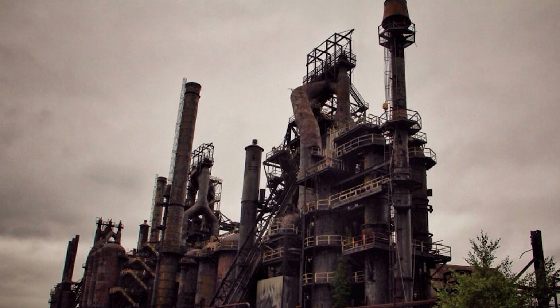Water quenching was fastest. The plate cooled from 1,625 degrees to 400 degrees in under 2 minutes. Fast cooling trapped the carbon in solution, creating a crystal structure called martensite, extremely hard but also extremely brittle. The plate emerged from the water quench hard enough to shatter glass, but brittle enough to shatter itself under impact. That's where tempering came in. Tempering involved reheating the quenched plate to 985 degrees for standard armor, or 425 degrees for high-hardness applications. At these temperatures, the martensite began to transform into tempered martensite, a structure that retained most of the hardness but gained significant toughness. The transformation was time-dependent.